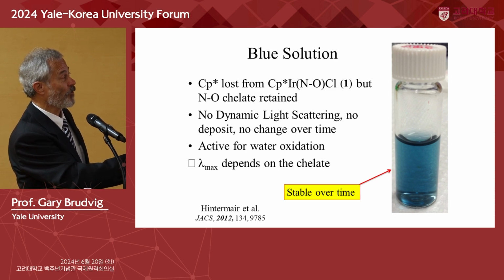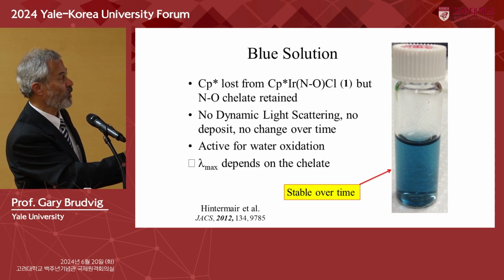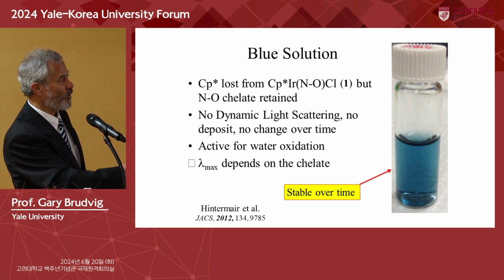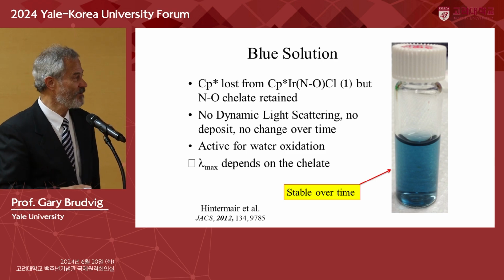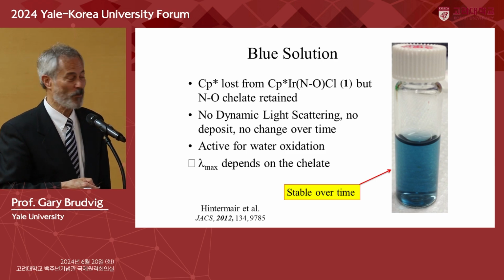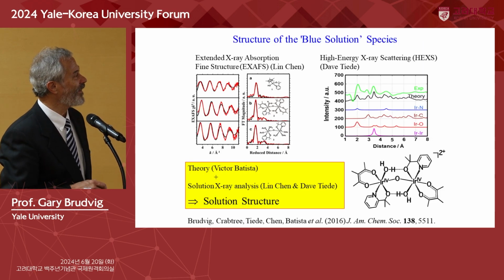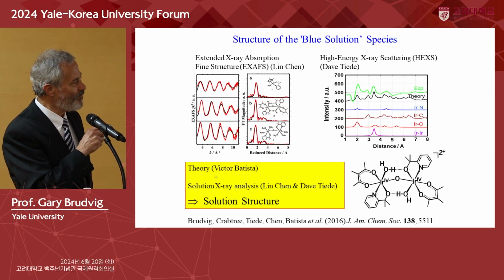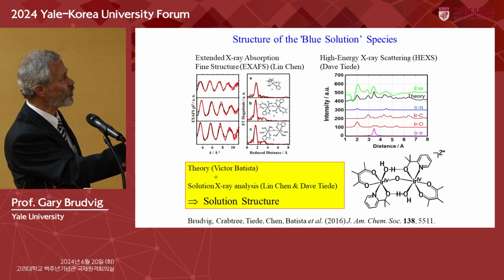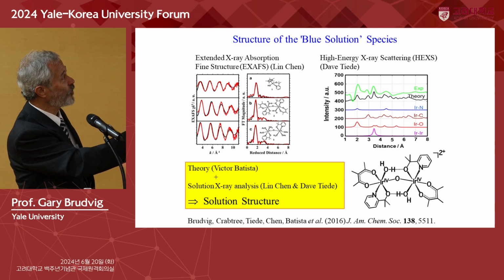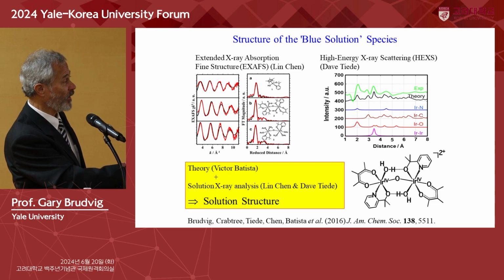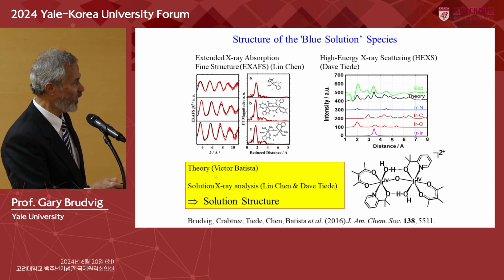It doesn't make any iridium oxide nanoparticles. We measure that by dynamic light scattering. It's stable over time, and it's very active for water oxidation. So here, after activation, we make a solution. We can keep that on the bench top for months. It's perfectly stable. And we can also characterize its structure. We haven't been successful in crystallizing it and determining the crystal structure, but we can use spectroscopy, X-ray absorption spectroscopy, XAFS, and high-energy X-ray scattering, together with theoretical modeling to predict that it's a dinuclear iridium complex with a single oxygen bridge, with coordinating waters and pyridine alkoxide ligands.